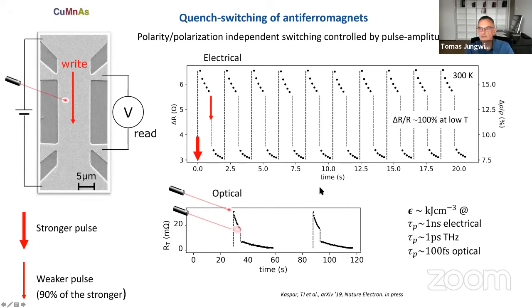What is equally promising to us is that we can also now use the same switching mechanism not only for electrical switching, but also for optical switching. So here is an example of delivering laser pulses. When we deliver higher intensity laser pulses, we switch the system into the high resistivity state. And when we deliver a weaker intensity by defocusing the laser, we can switch the system into a lower resistivity state. And this switching can be done even with a single 100 femtosecond laser pulse. And so we have now ultra-fast switching in terms of the pulse length, where we can go all the way from DC to a single femtosecond laser pulse.